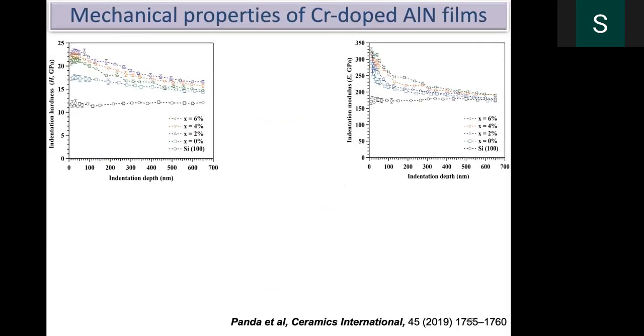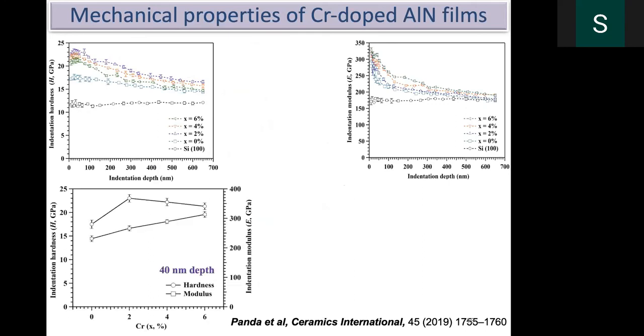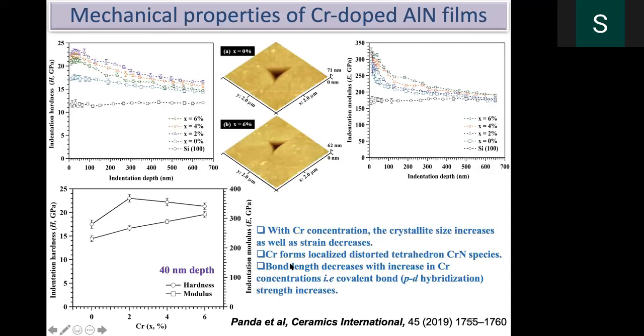And these are all just fittings from the X-ray absorption spectroscopy. Again, we did the continuous stiffness measurement. In this case also there is a sudden initial lower value at the surface, but when you go beyond 100 nanometers, the hardness stabilizes. If I plot at one particular depth, like 40 nanometers, how the hardness varies, this circled one is hardness. It increases up to 2% of chromium. After that, there is no big difference, but there is a slight deviation. That means hardness can be engineered by adding chromium into the aluminum nitride system.